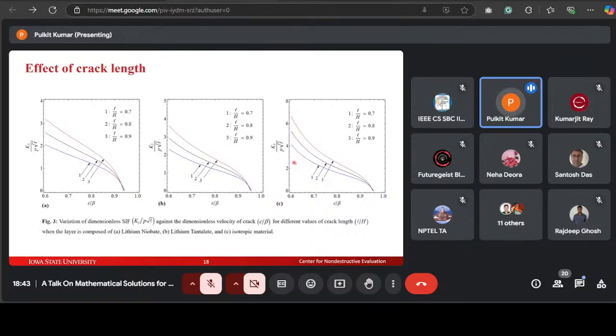So these are the key findings of this study. The stress intensity factor decreases continuously as crack velocity increases due to the plane wave propagation, but later on it settles down to 0 when the velocity of the crack approaches the velocity of the wave. And the longer crack exhibits the higher stress intensity at the crack tip. Moving the point load closer to the crack tip increases the stress intensity factor. And the stress intensity factor is higher in the isotropic materials than in the monoclinic layers. And among the monoclinic layers, the lithium tantalate shows higher stress intensity factor than the lithium niobate. So now we move to the next part of the talk.